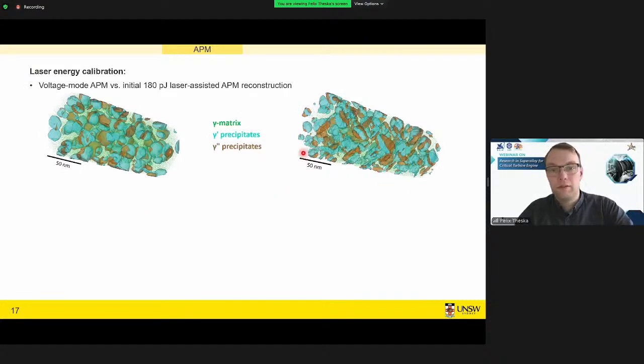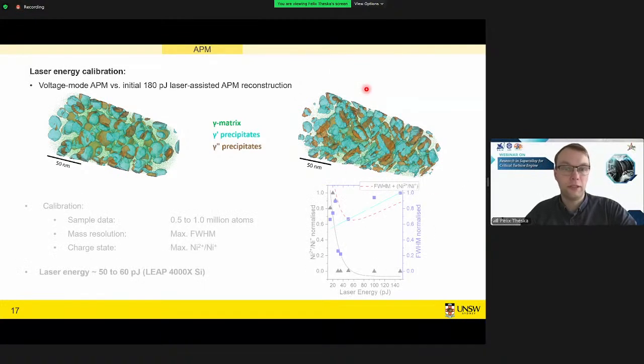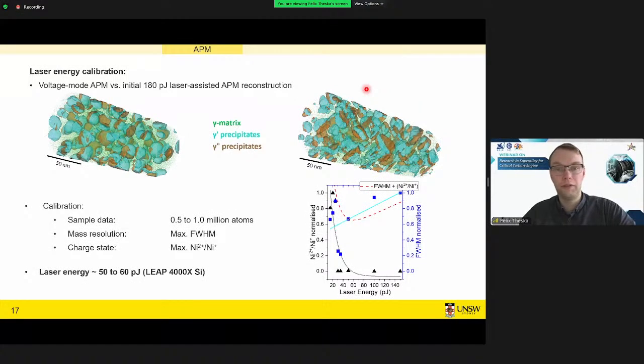Just a short slide on the laser energy is here. We cannot use any type of laser energy. As you see on the left-hand side, a voltage mode, and on the right-hand side, a very high laser energy. So if we go too far with the laser, we may even distort the resulting data, which is then not useful anymore. What we did here was have a look at the mass resolution and different charge states to calibrate the laser energy, and then could use actually 50 picojoules for this material and this microscope design.